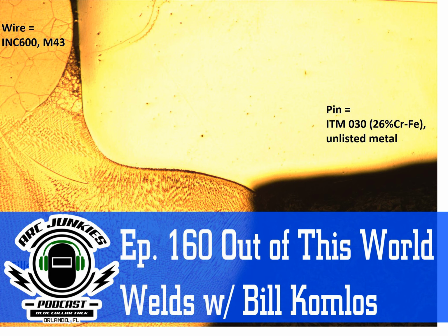We often will weld as an alternate to that ferritic stainless to carbon steel flange that cracks out all the time for my customer. If we welded with the Inconel filler metal 82, it would never crack. It'd stay right in there because it's not affected by cycling heating. It doesn't like magnesium. The magnesium would eat every piece of nickel out of there. And one of these days, I'll show you a groove that shows that just perfectly.